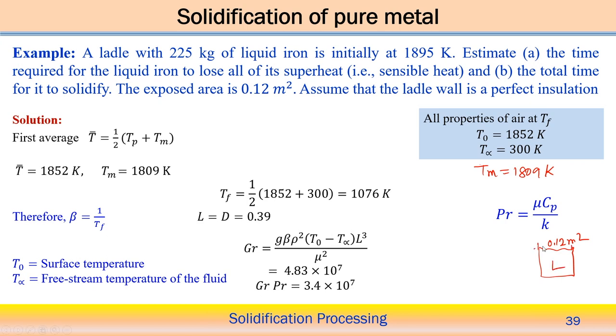So, how to handle this particular problem? We assume the ladle wall is a perfect insulation, that is, all other surfaces are perfectly insulated, so there is no heat loss from them; whatever heat is lost is lost from the top surface only. Now, we need to consider convective and radiative heat transfer from the top surface, and the cross-section area associated with the top surface. The outside medium is air, and T infinity is an air temperature of 300 Kelvin. We are considering natural or free convection in this case, and from there we estimate the total solidification time for the two different cases.